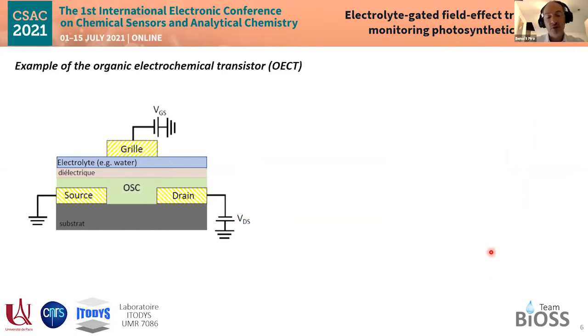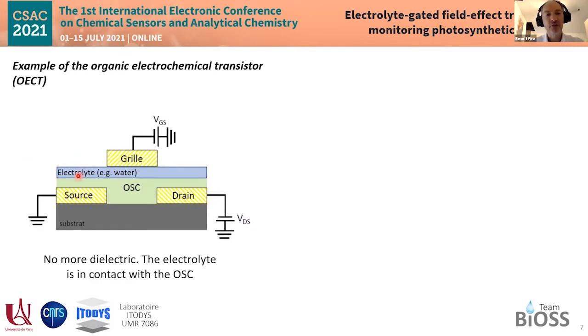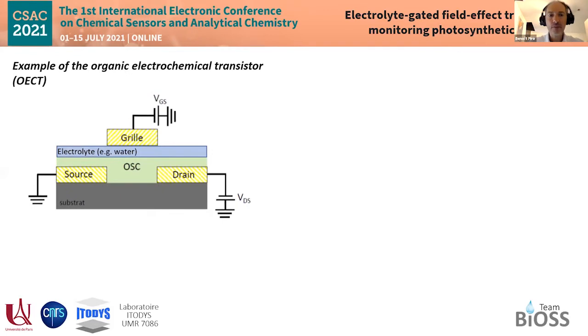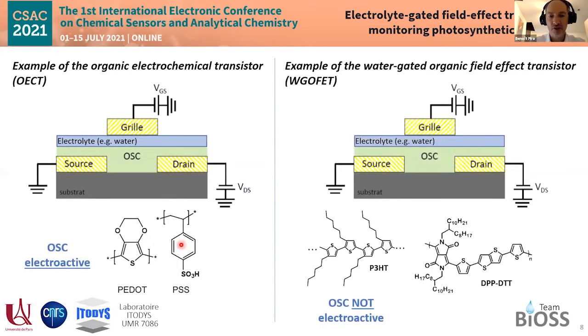There are also organic electrochemical transistors, or OECTs. Again, the structure is very similar, but in that case, the dielectric is suppressed so that the semiconductor is in direct contact with the electrolyte. But in this case, the semiconductor must be electroactive and is typically p-doped by polystyrene sulfonate, PSS. I will not give an example of that because I want to go directly to the water gate organic field effect transistor, or electrolyte gated, E instead of W, organic field effect transistor, the structure of which is absolutely similar to that of the OECT, but in that case, the semiconductor must not be electroactive.